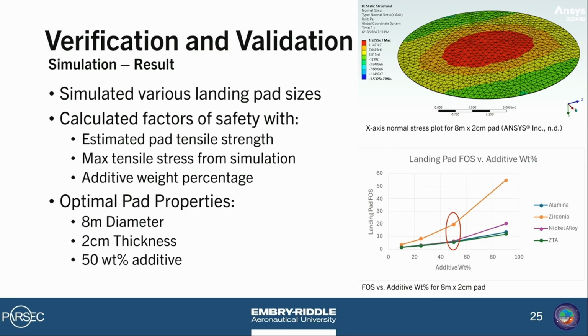And we did this for landing pads of various sizes in an attempt to maximize our factor of safety and minimize the amount of additive mass required for the pad. We ended up finding that a pad with a diameter of 8 meters, thickness of 2 centimeters, and consisting of about 50% additive by mass had optimal properties, including factors of safety greater than 5 for all of our additives. As you can see in the bottom plot there, all those points circled in red.